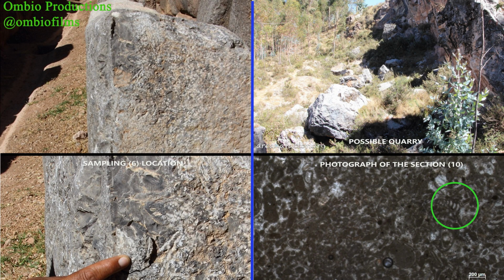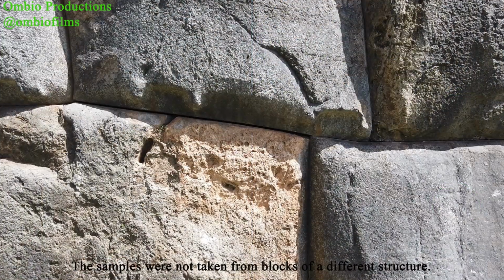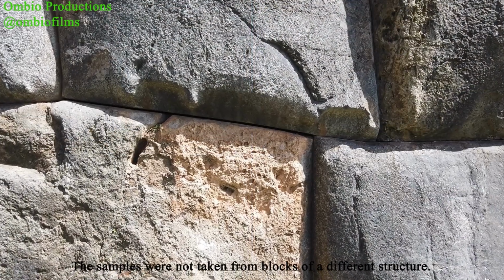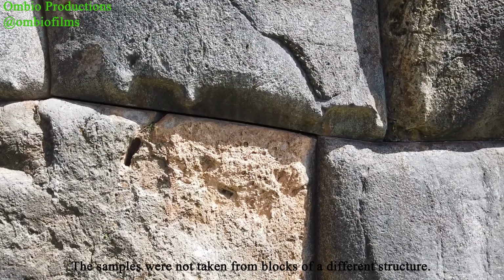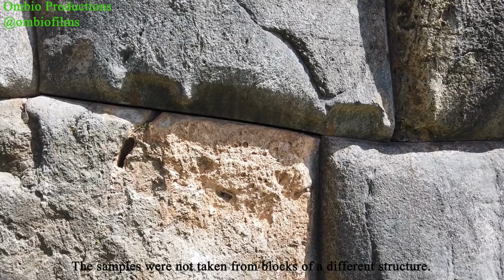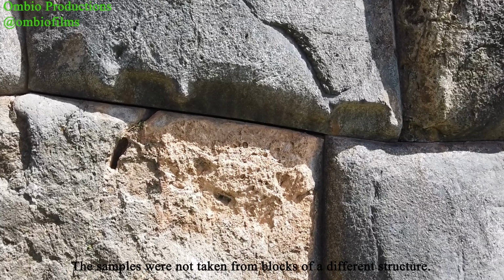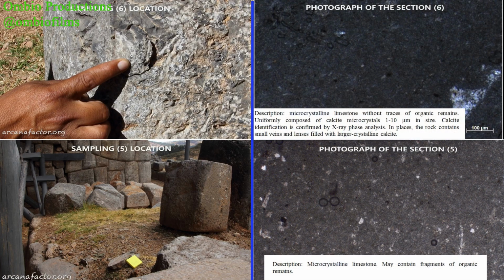The limestone material taken from the blocks was dense and lacked visible organic remains, such as shells, whereas the single sample taken from the so-called quarry, or rather from a nearby limestone outcrop, had a different structure. However, to properly establish a match between the stone used in the blocks and that of the quarry, multiple samples should have been taken from limestone outcrops with the most similar structure. The analysis determined that the stone of the blocks is microcrystalline limestone, with minimal or no organic remains.